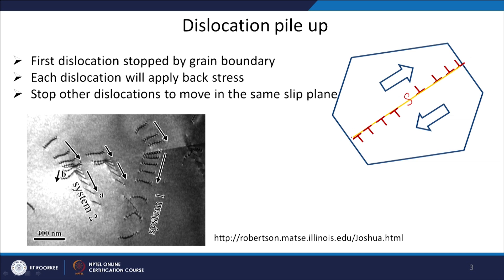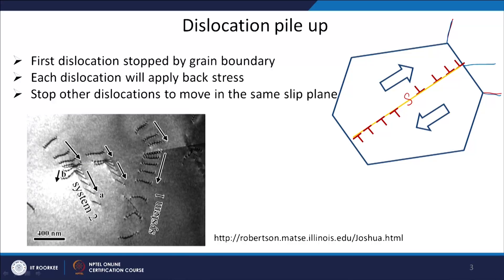The reason is that suppose my dislocation is moving on a crystallographic plane, and the next grain — so this is my next grain boundary. In the next grain, as I already told you, the difference between this grain and the next grain close to it is that there will be a change in orientation. So in the next grain, this particular plane may be oriented in some other fashion. The dislocation, when it is moving in this plane, cannot just start moving in another orientation. So grain boundary is a very strong barrier.